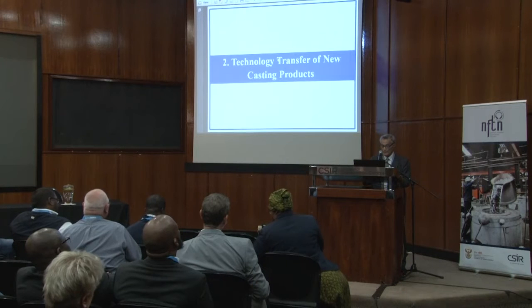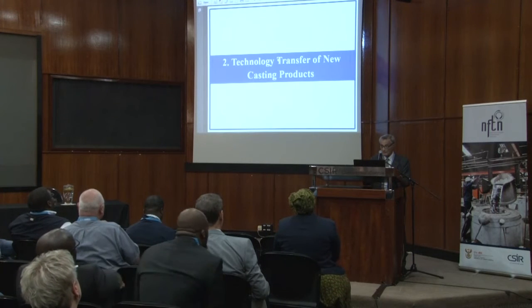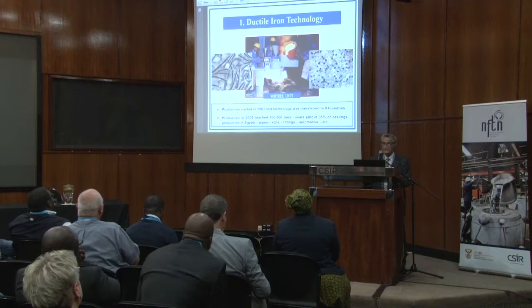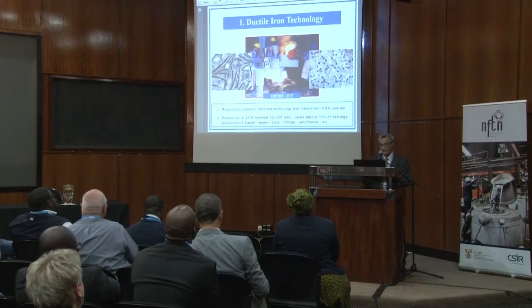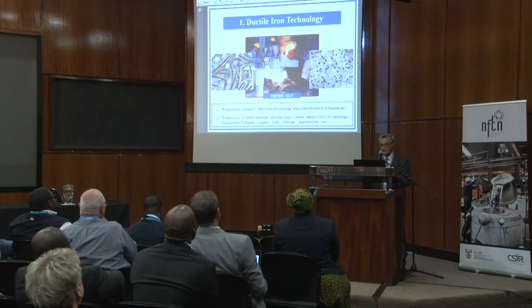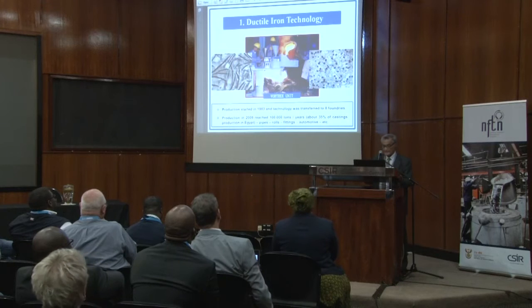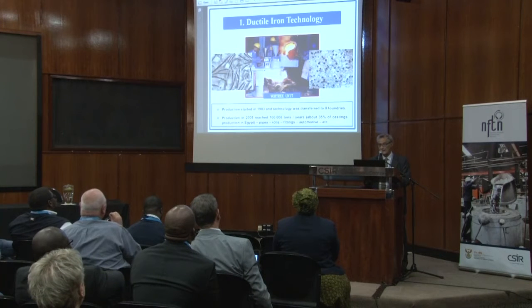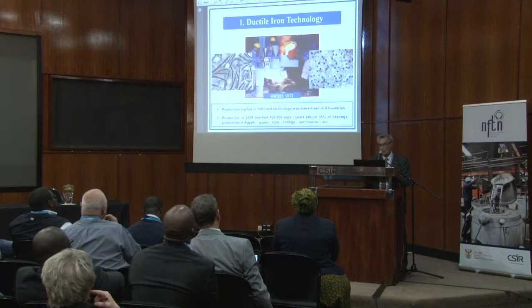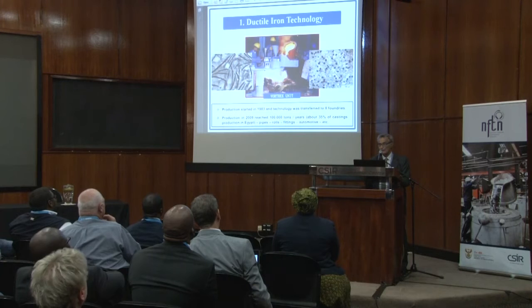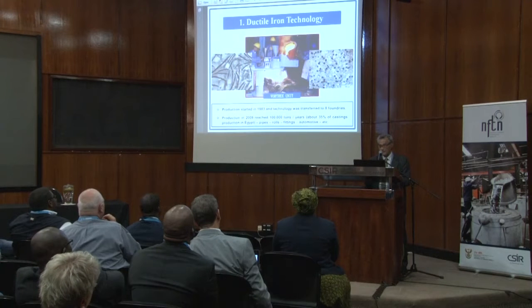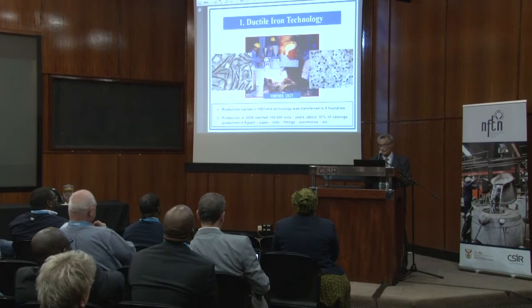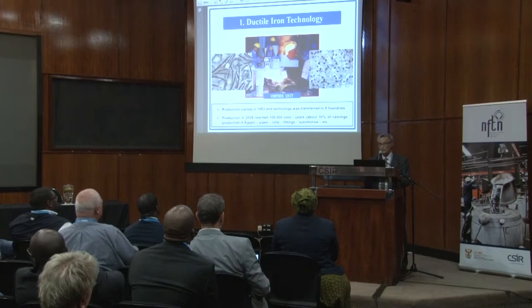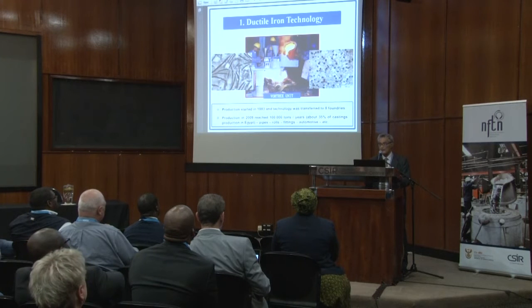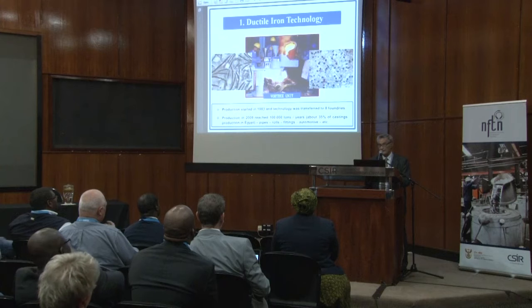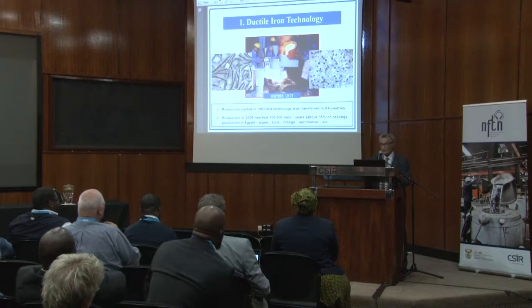And now I go to the technology transfer of new casting products. I give some examples. We started in 1983 with the introduction of ductile cast iron for the first time to our foundries. If you look at the photo at the right hand side, it's gray cast iron, where the carbon or graphite exists in the form of flakes with sharp edges or sharp tips, which act as stress concentrators. That's why gray cast iron is known as a weak and brittle material. In 1949, with the first development of ductile iron or spheroidal graphite iron, with very small additions of magnesium up to 0.04, 0.05%, the graphite flakes were transformed to spheroidal graphite, neutralizing the detrimental effect of the flakes.